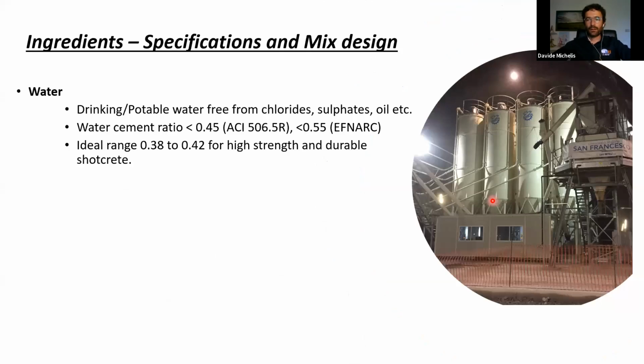Water, along with the cement, I think is the most important component to be properly dosed and used. Of course, we need to use tap water, which should not have any chloride, sulfate or oil inside. The water cement ratio in the mix design should be as much as possible lower than 0.45, because the quality of the shotcrete will rise a lot using a low water cement ratio. The ideal range is between 0.38 and 0.42, and with these values we can achieve high strength and durable shotcrete, and during the application we can really reduce the rebound. We can even face difficult situations like water at the tunnel face.